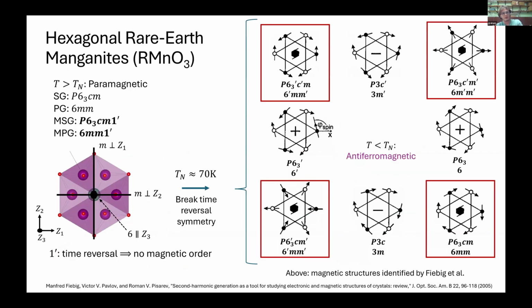These are also antiferromagnetic. So when we talk about magnetic symmetry, we use the magnetic point group, and we include time reversal as a symmetry operator. If time reversal exists in the magnetic point group by itself, so 6mm1' for the paramagnetic phase, this means the material is not magnetically ordered. You apply time reversal symmetry, and this basically flips all the spins of the manganese ions.